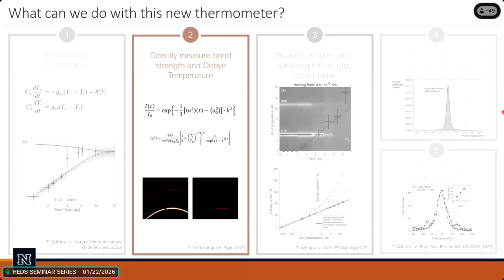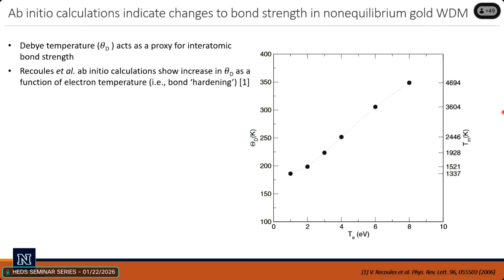Okay, I'm going to tell you about one more physics thing which we did, which is measuring the bond strength and the Debye temperature in samples. People might not know too much about bond strength and Debye temperature, but there is this thing called bond hardening. If I heat up the electrons in the system but keep the ions cold, so I have a very non-equilibrium system, hot electrons and cold ions, the bonds get stronger in metals. At least this is the prevailing theory.